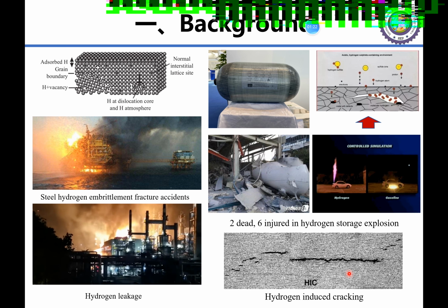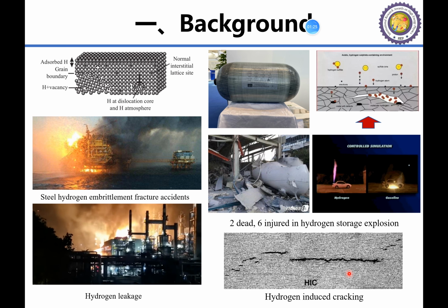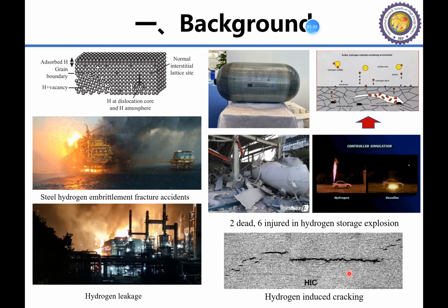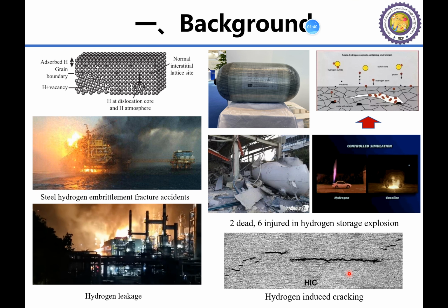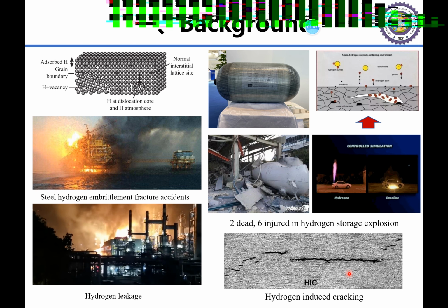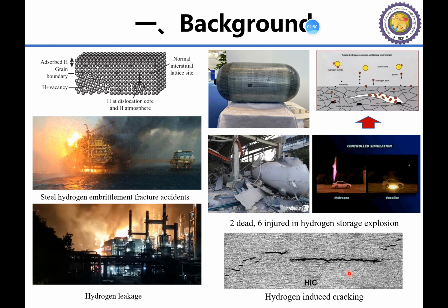Hydrogen embrittlement in materials is one of the most important issues affecting the rapidly developing field of hydrogen storage. The current understanding of hydrogen embrittlement is that hydrogen in the environment dissolves into the steel and migrates and accumulates towards areas of steel stress concentration, for example, crack tips, eventually assisting crack nucleation and extension into failure.